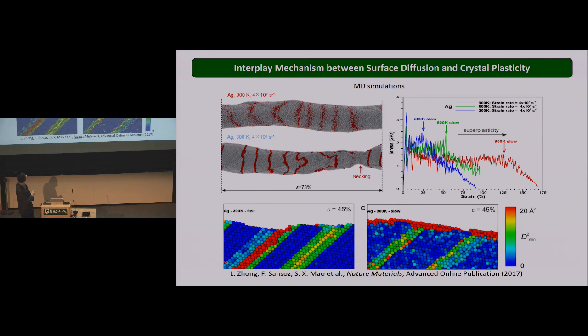And the detail shows this. When you allow for diffusion, there is definitely an absence of the steps that form. So you see a lot of deformation localized on the surface that is consistent with atom diffusion on the surface that coincides with the nucleation of the dislocation.